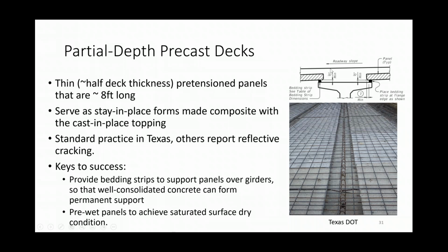And the reason why it's there is because they want to make sure the cast-in-place concrete gets under the precast deck panel and is well consolidated under that deck panel, and it becomes a good permanent support for that deck panel. So the cast-in-place consolidated concrete is the support permanently through the use of these bedding strips. And the second key point they mentioned was that, just like you've heard me talking about UHPC, really bringing these panels to the saturated surface dry condition by pre-wetting them, you get great bond between the 2.